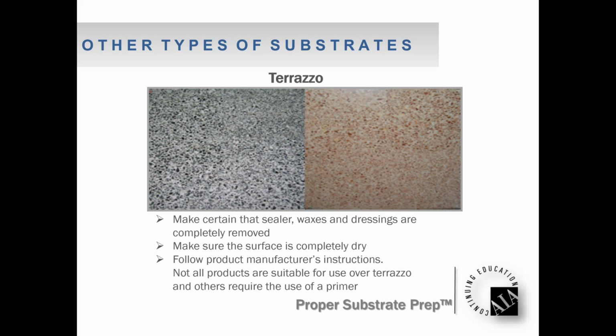Okay, if it's concrete terrazzo and you hypothetically shot blasted it, I mean, you may be down to porous concrete. You've blasted it to open up the polished surface. And in that case, it may require a different primer that's able to soak in and grab onto the pores, being that that's concrete terrazzo. Certainly bring your manufacturers in to help with those types of recommendations and discussions.